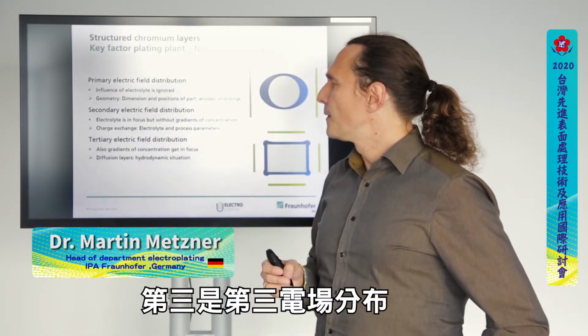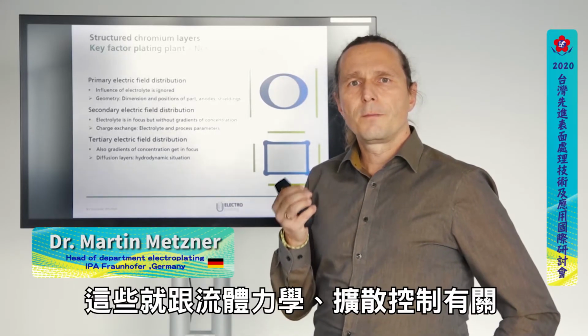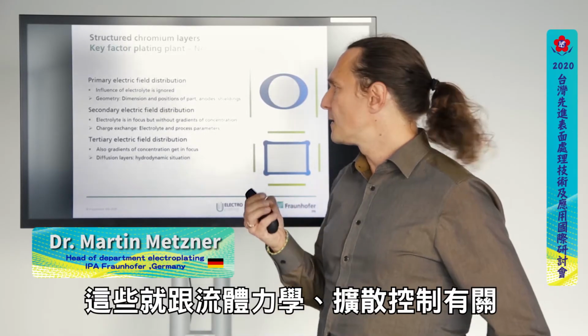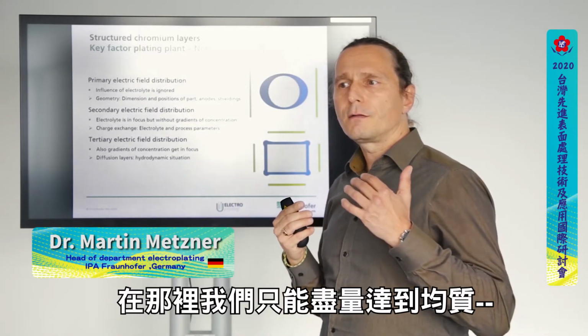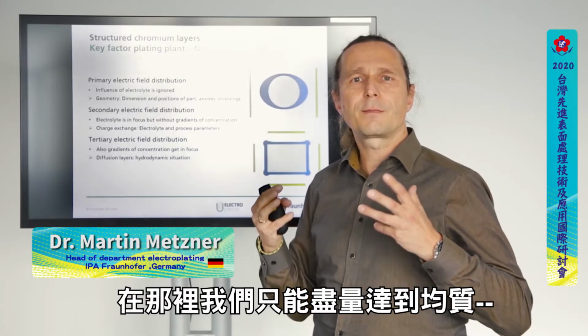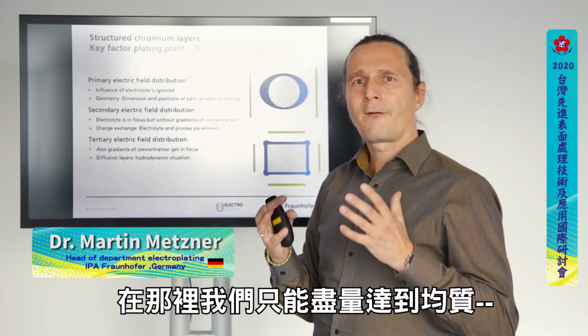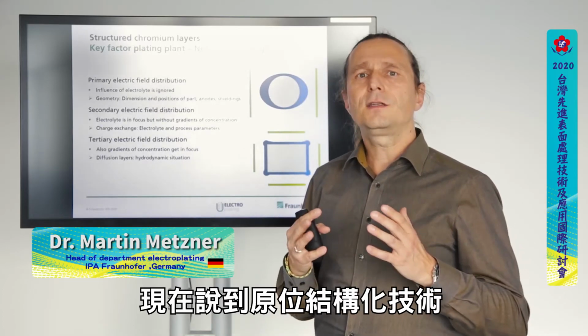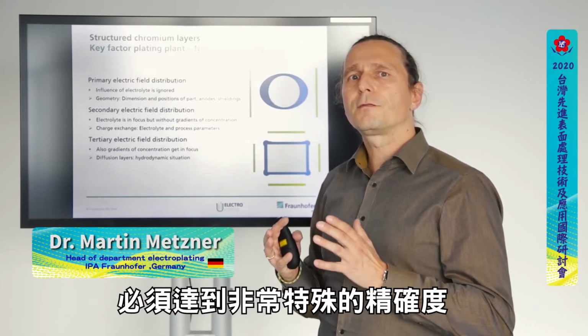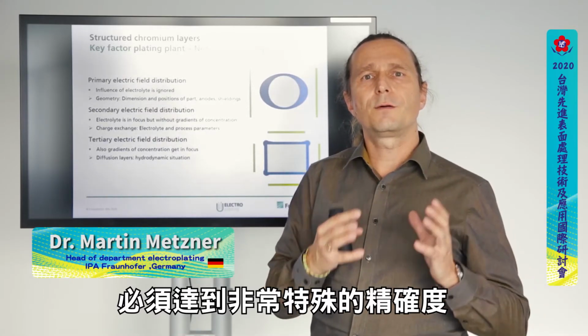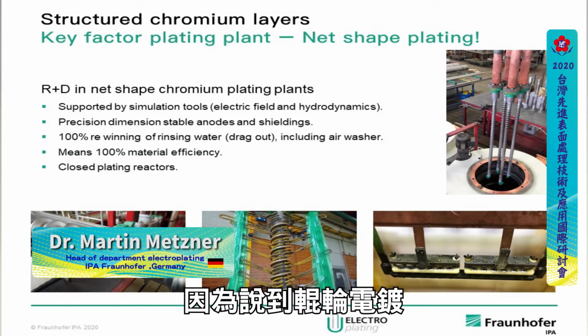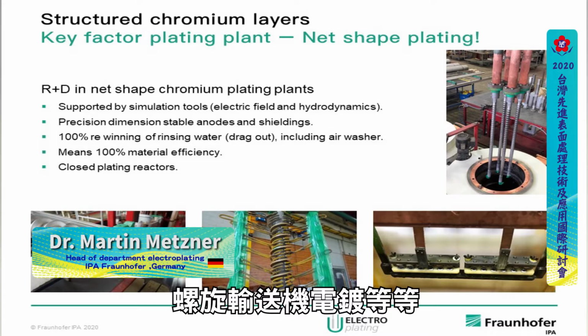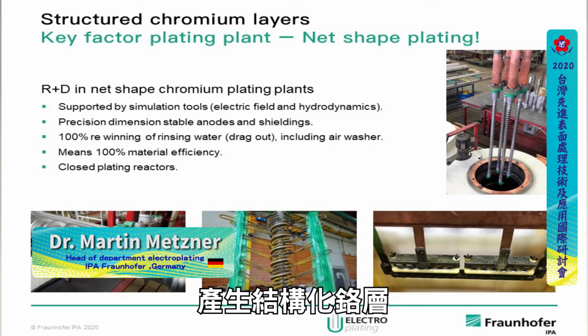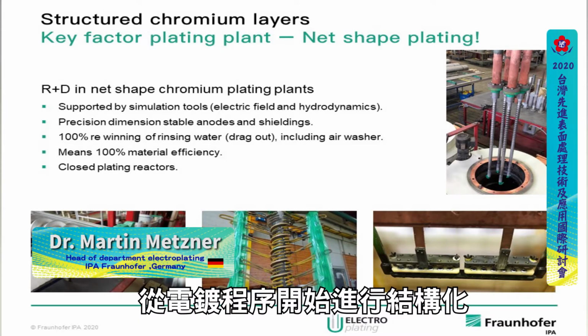And the third one, the tertiary electric field distribution. This is everything concerning hydrodynamics, diffusion control. There we cannot do anything else than make it as homogeneous as possible. And now when we talk about an in situ structuring technology, then of course we have to go into a very special precision, because when we say we plate rolls, we plate something like a conveyor screw like that with a structured chromium layer and do the structuring from the plating process.